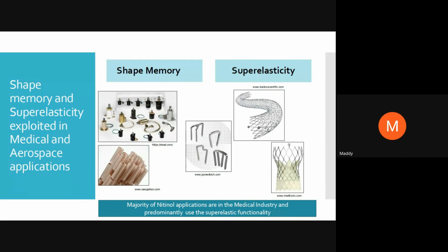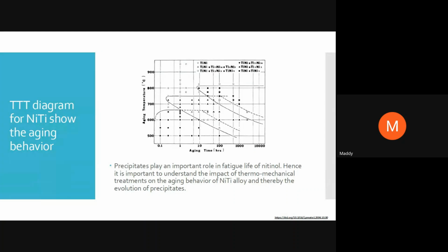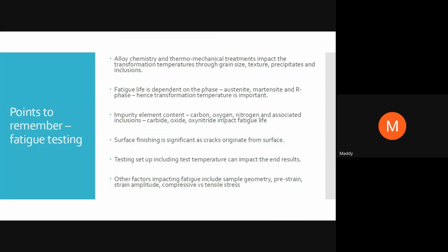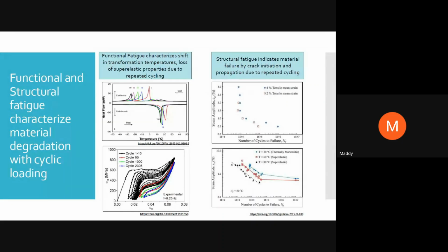One thing I forgot to mention in the fatigue is, if you could just go back to the previous slide, I think slide number, let's say 14. Sorry. I want to mention something here. Unlike your conventional material where you have stress versus number of cycles, in nitinol they plot strain versus number of cycles for the simple reason that if you look at the stress-strain response in the bottom left corner, you see that at a particular stress, the strain increases. So that's the reason why they don't go with stress, but they go with strain. So with varying strain, the life cycle of the product is evaluated.